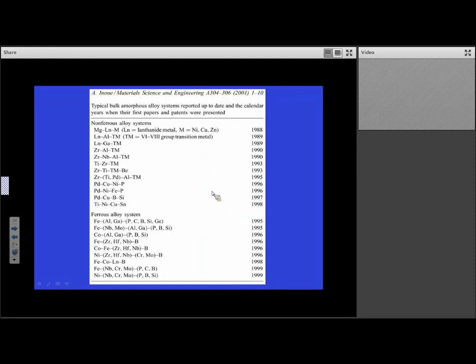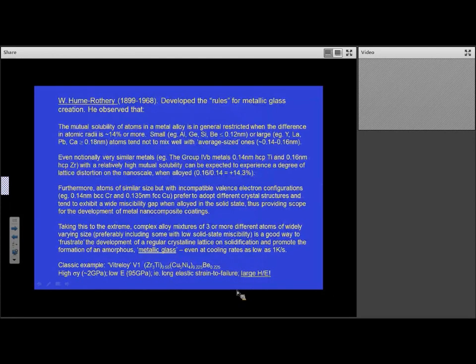Those of you who are unfamiliar with glassy metals, the person who developed the theory for glassy metals, I won't read through this, but Hume-Rothery was the chap we can thank for the different theories. It's all to do with the mutual solubility of atoms in the metal alloy, and it's generally restricted when the difference in atomic radii is 14% or more, and if they're large or small, they don't tend to mix with average size atoms. So even notionally very similar metals with a high relative mutual solubility can be expected to experience a degree of lattice distortion on the nanoscale when alloyed. Also atoms of a similar size with incompatible valence electron configurations prefer to adopt different crystal structures and tend to exhibit a wide miscibility gap when alloyed in a solid state, thus providing scope for the development of metal nanocomposites and also the metallic glasses, the whole of this theory.